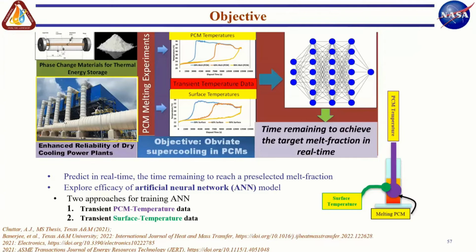So it's kind of somebody putting their ear onto a wall and eavesdropping on their neighbor. In essence, you are not measuring the temperature of the PCM itself, you're just measuring the temperature response of the container at different heights. And from that, you're trying to back calculate how much of a melt fraction you have at a particular time. And then you are trying to predict how much time you have before you hit, let's say, an 80% or a 90% melt fraction.